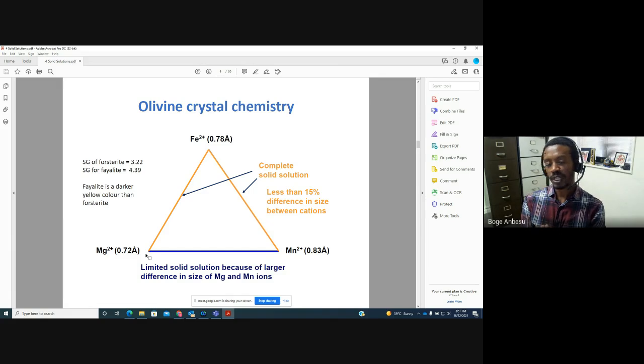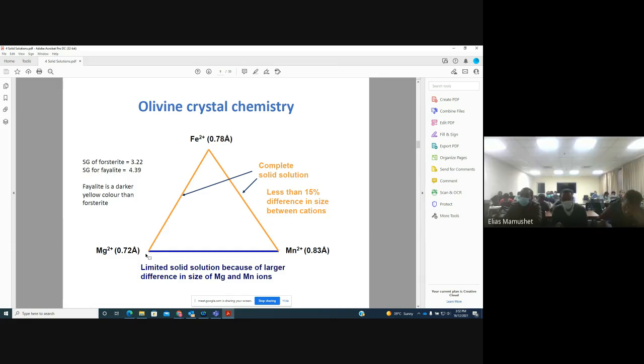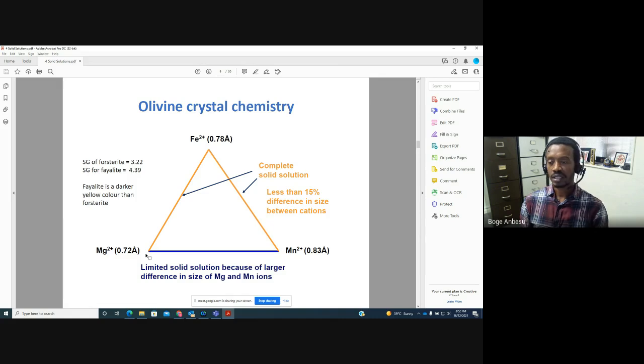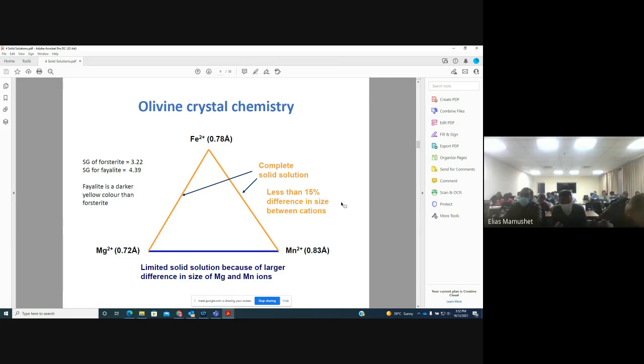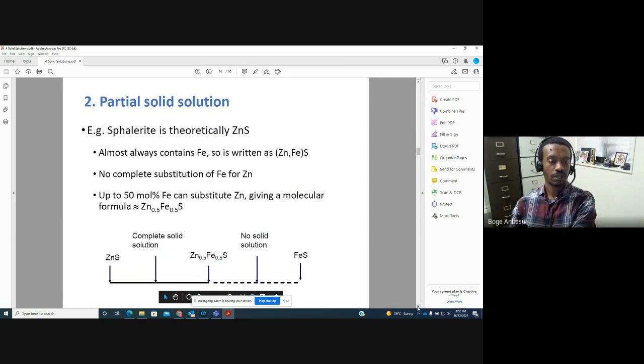As we know, if specific gravity is different, then based on that, minerals may not be recovered completely. Okay, because instead of being heavy, some are lighter because of that possibility of solid solution. And sometimes they appear different in color. For example, as you add more and more iron into olivine, you have the color changing into darker and darker. So as well, impurities can affect color, appearance, and so on. And sometimes they may even distort the crystal chemistry. Okay, because if you fit a slightly bigger atom, although it's within the 15% range, sometimes that can distort the crystallography or the crystal lattice of a mineral. And again, that will have a significant influence on how the mineral appears.